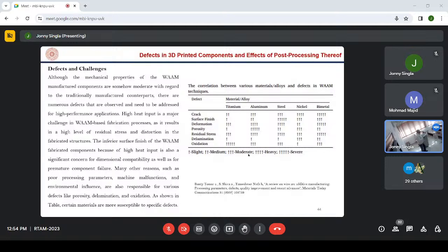We already discussed layer thickness, hatch spacing, scan speed and laser power, and the optimized range is provided as per the literature. Then we can use this as a base parameter for bimetals. Yes, this can be used, and then with a little trial and experiment, you can optimize.